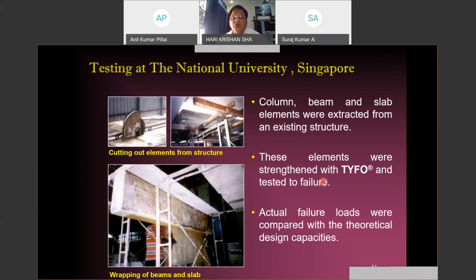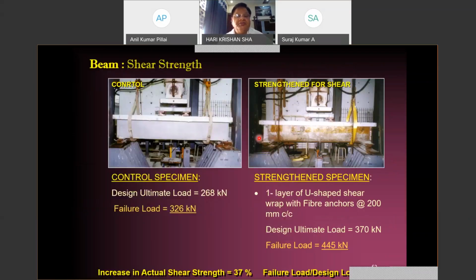The actual failure loads were compared with the theoretical design capacities, and it was found that there was a significant increase in the load carrying capacity under different loading conditions. So when these elements were extracted from the real structure, they were wrapped for testing in shear, in flexure, and in compression.